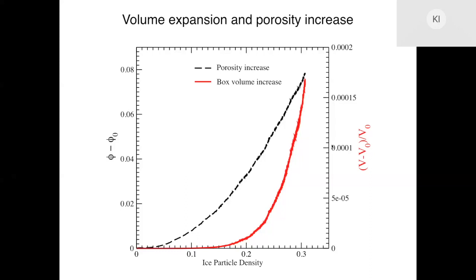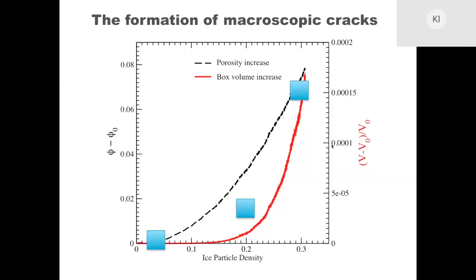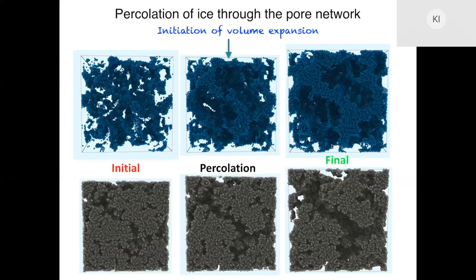So we start observing volume changes macroscopically. So we're going to look at 3 points in detail to see what is happening. The first point is where we have the increase of porosity, the second where we have the macroscopic increase, and the final state. So initially, when we have the porosity increase, if we decouple the two networks, so if we plot the cement on the bottom and the ice on the top separately, we see that we have formation of ice, but it all stays inside the pore.